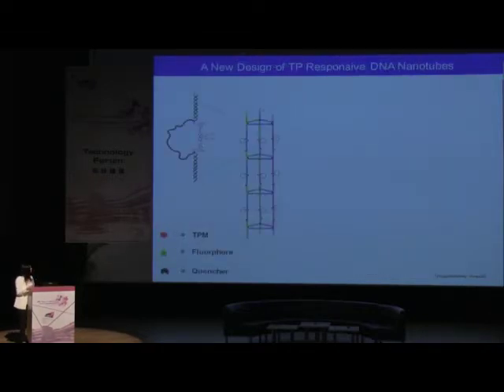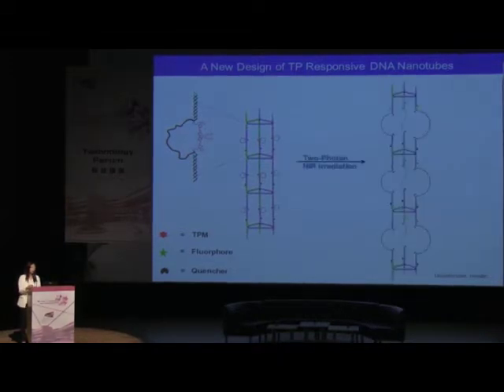So our idea here is to try to modify the nanotube with a two-photon labile molecule as shown here with red color, and design the tube with some hairpin, the single strand sticking out. So what happened is that once we excite with the two-photon laser, basically the photoreactive molecule should cleave by itself, and then expand the cavity along the nanotube and become a flexible nanotube now.